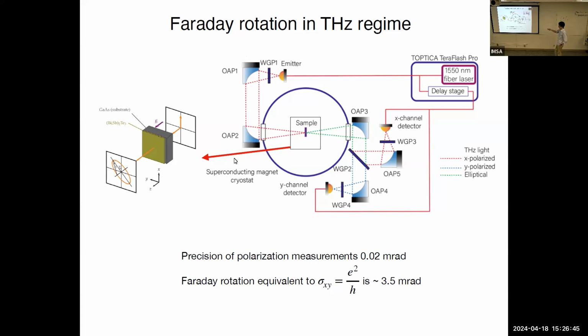To do that, you first have to generate this light, which is done through this optical setup here. This emitter emits linearly polarized light, which is focused by different mirrors and lenses. Then we have a sample placed inside a superconducting magnet cell, because we have to apply a large magnetic field. After coming out of the sample, the light is elliptically polarized, so we have to split the beam into x and y components so that we can measure them separately, and their ratio gives us the Faraday rotation. To give some idea how large these rotations are, the Faraday rotation equivalent to e squared over h in the quantum Hall effect is about 3.5 milliradians, which I believe is about 20 millidegrees. The precision we have in the setup is 0.02 milliradian, which is almost 1 millidegree. So we absolutely have the precision to be able to measure this accurately.